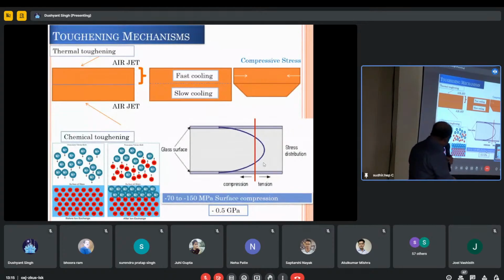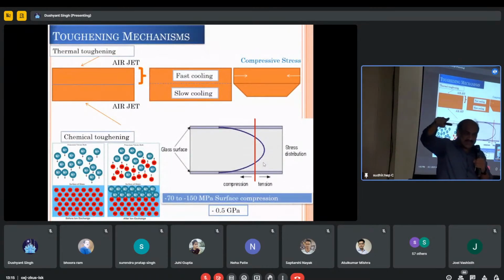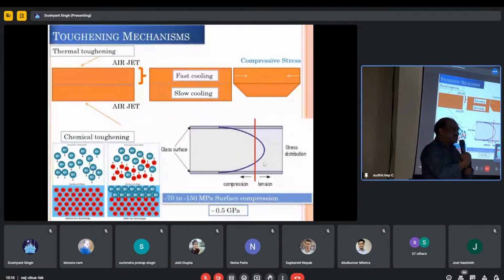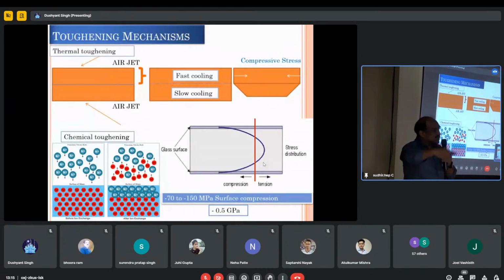So in chemical tempering, what happens exactly? There are sodium ions in the glass, and the glass is exposed to potassium nitrate solution at high temperature. The smaller sodium ions are replaced with bigger potassium ions. These bigger potassium ions create surface compression. So the small cracks already present in the glass surface are compressed, and it gives a lot of strength to the glass. Gorilla Glass mostly relies on this kind of technique. I will show how Gorilla Glass is made also.